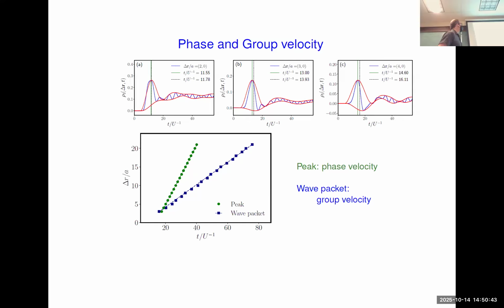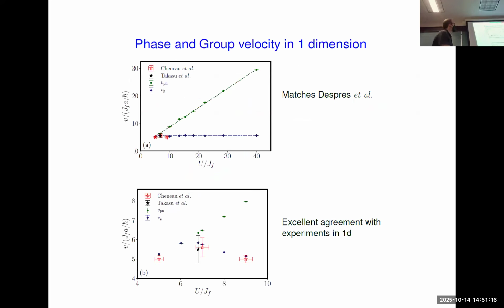And then we can also look at the phase and group velocity. If we look at the position of the peak of the single particle density matrix, we extract the phase velocity, and if we look at the center of the envelope of the wave packet, that gives us the group velocity. And we can see here, this is for a given value of U. We see a clear difference between the phase velocity and the group velocity. And then we can plot this for a variety of values of U over J. And if you cast your mind back to earlier in the talk, we see at least qualitative agreement with Despres et al. Here the phase velocity is larger than the group velocity.